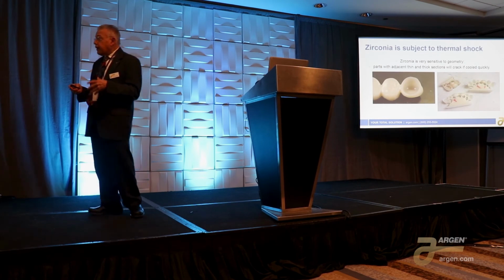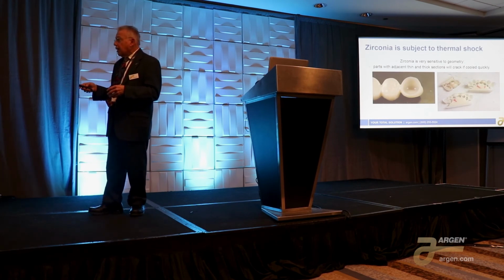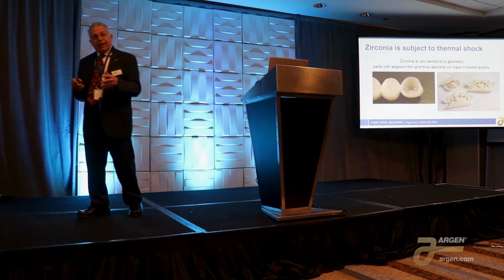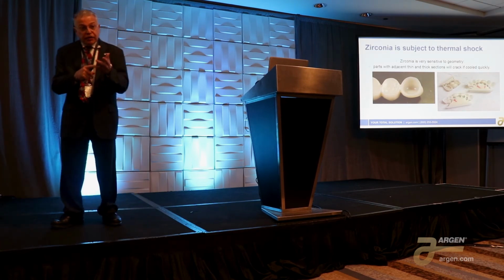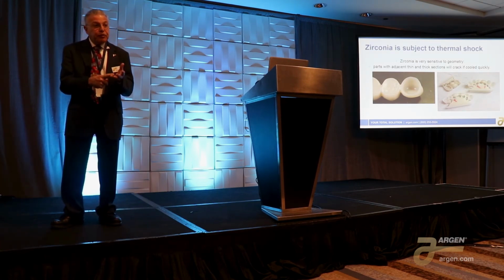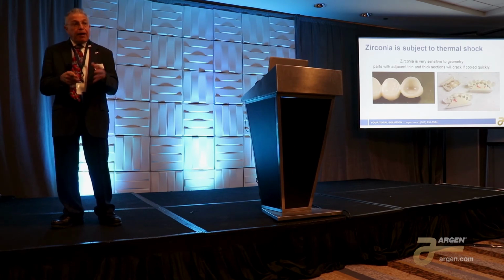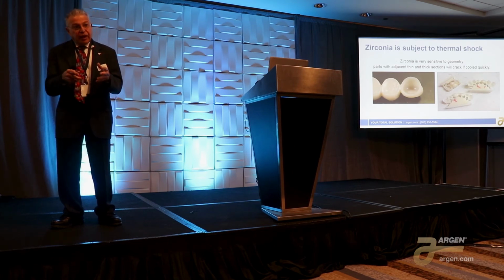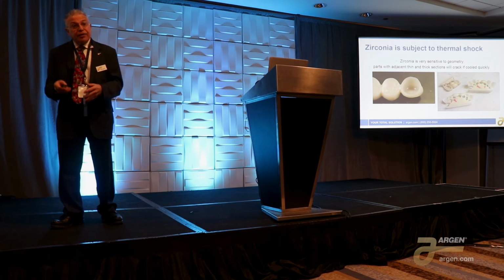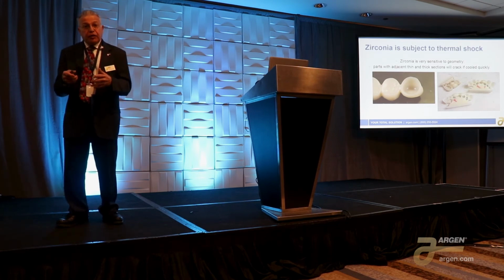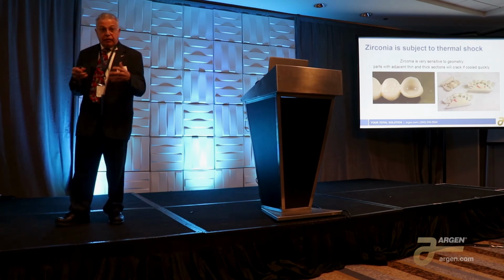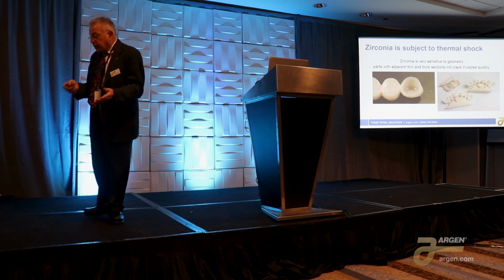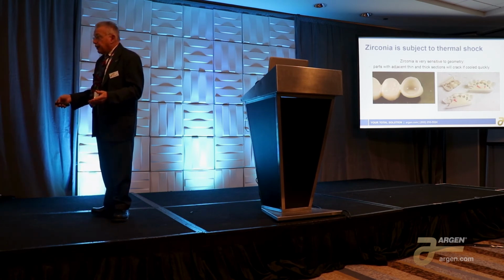Now, as I said, zirconia is very sensitive to thermal shock. So what does that mean? That means that because it doesn't conduct heat, geometry is very important. So anytime you have a thick section next to a thin section, you have to go slower. And this is the main reason why the bridge cycles are so long, because you obviously have a pontic next to an abutment. And here you have a very thick section compared to this thin section.